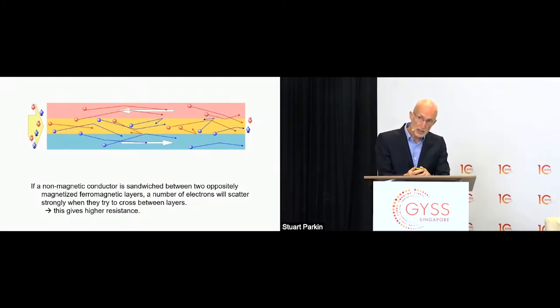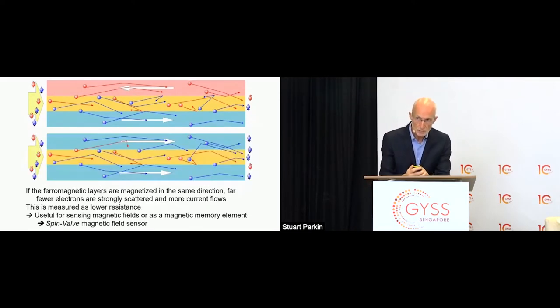On the other hand, if we rotate the two magnetic layers so they're both blue, they both have the same direction of magnetization, now the blue electrons can be weakly scattered everywhere in the system, and this leads to a lower resistance. So we've built now what I call the spin valve. And this spin valve is a device whose resistance depends on the directions of these two magnetic moments. Low resistance when the moments in the sandwich are parallel, and high resistance when they're antiparallel.